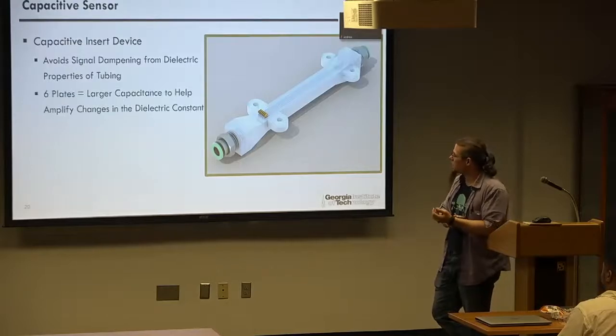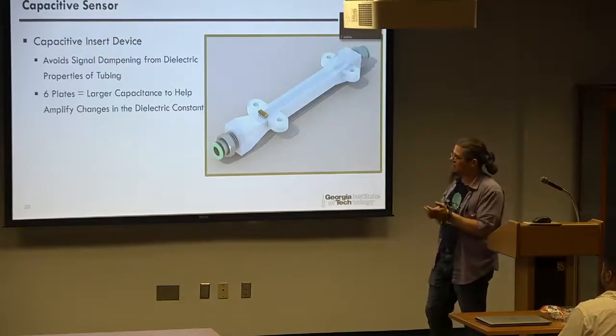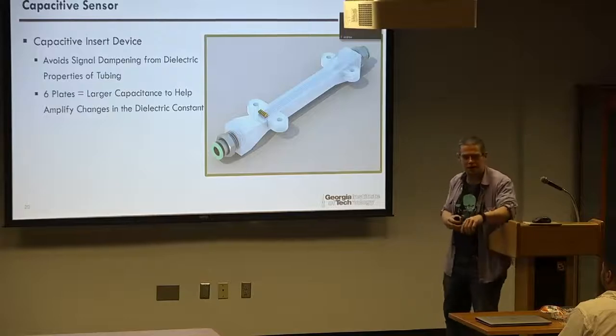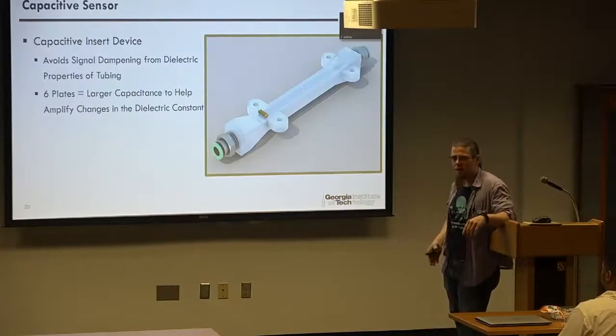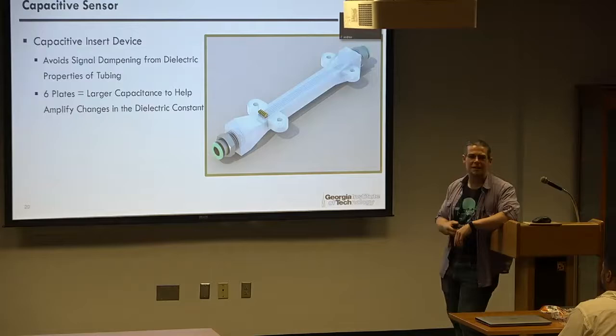We've got 6 plates. This gives us a larger capacitance to help amplify changes in the dielectric constant. We can't do more than 6 plates because if they get closer together, then we end up with them too close together for the powder to flow between.